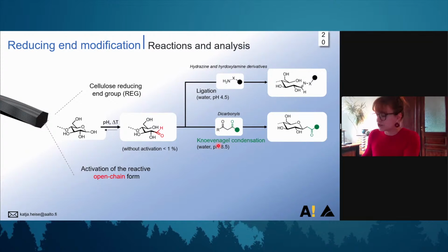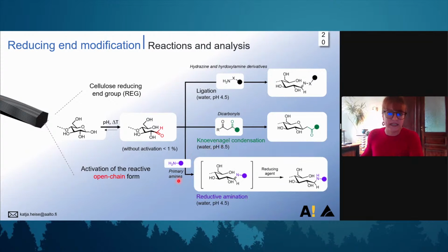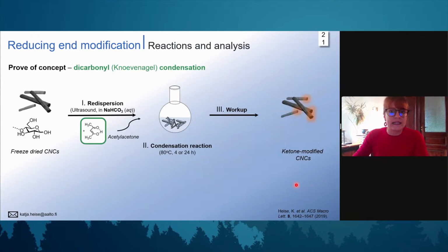and at basic pH. And the third possibility, something we've been studying quite widely with Gwendoline Delpierre, is the use of primary amines to attach them under reductive conditions to the reducing end, and what you obtain are secondary amines. So it's really interesting for bioconjugation, for example. Okay, but let's talk a bit more about the Knoevenagel condensation. It's a reaction we use more or less as a proof of concept.